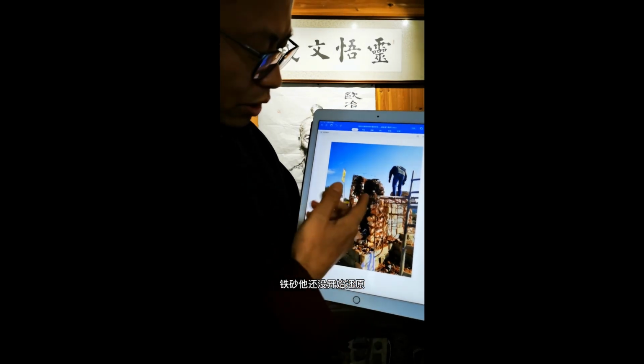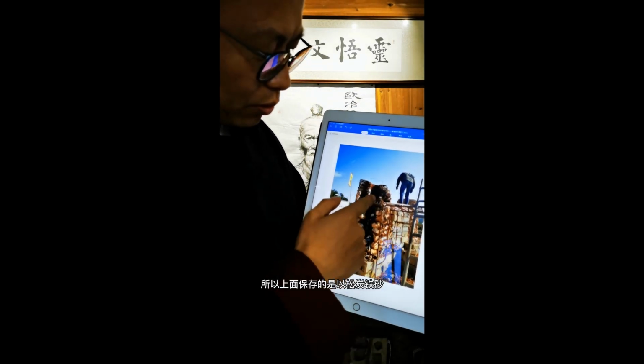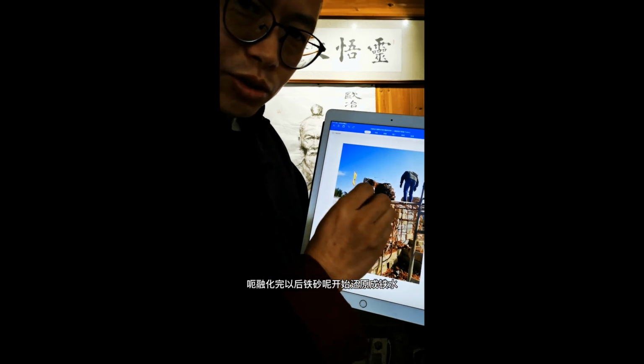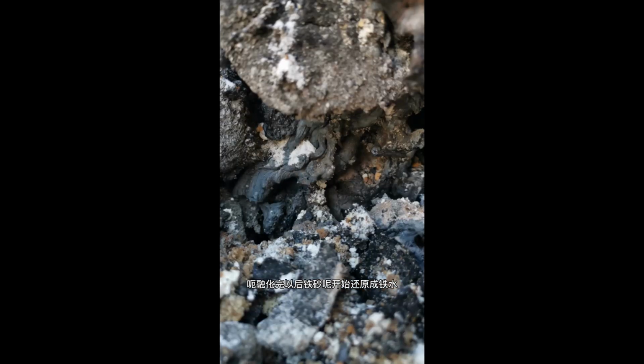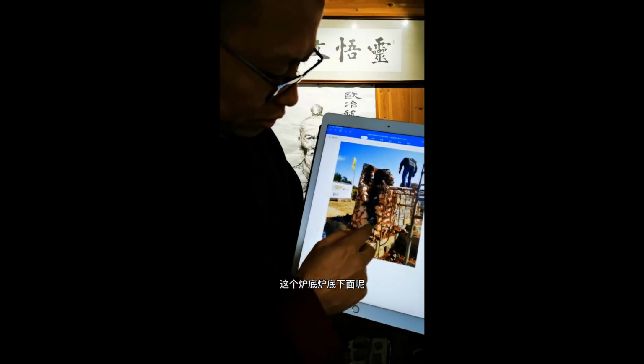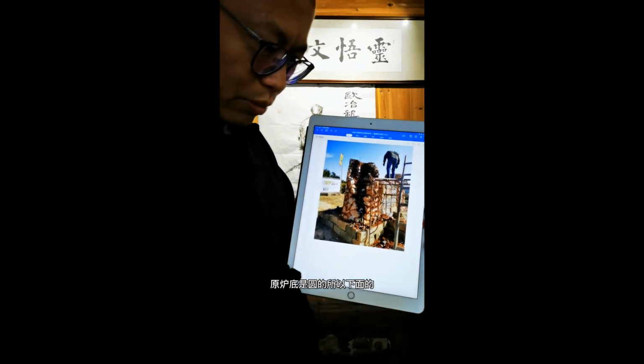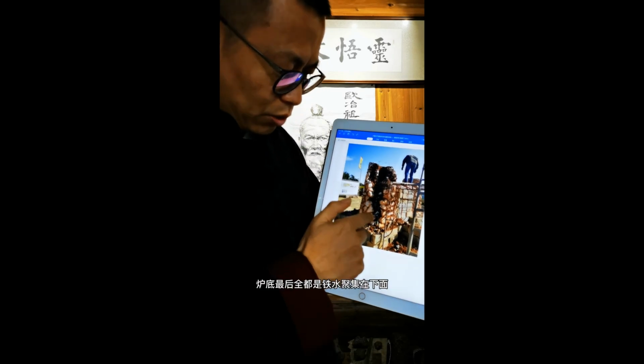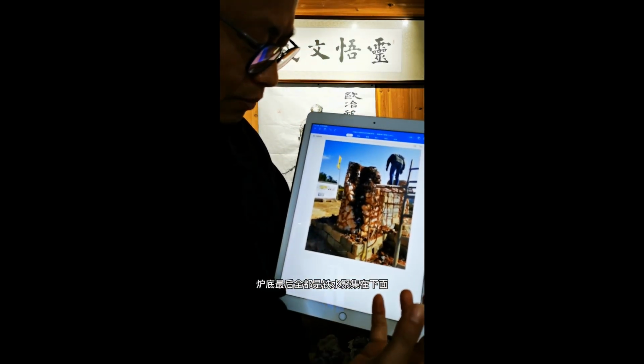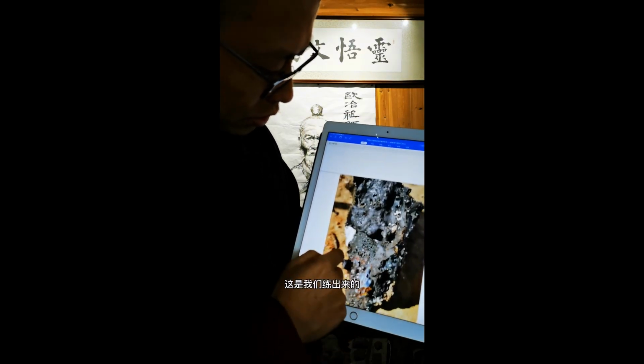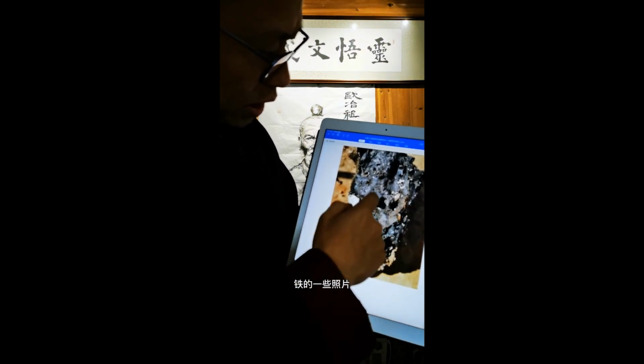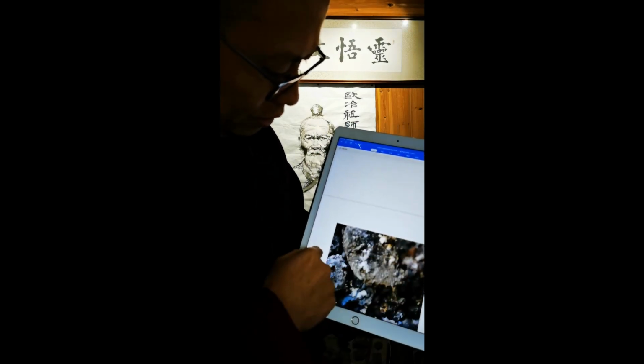At the upper side, the temperature was not that high, and the reduction didn't begin until very late. So you can still see some charcoal and iron sand in the furnace. And at the bottom, the temperature was much higher, and the iron sand began to melt, and then the reduction began. After that, the melted iron flowed to the bottom, to the hearth. The hearth has a curve, just like a basin. And at the hearth, you can see all the melted iron gathered there, as this picture shows. This is the iron we got. There's another picture.